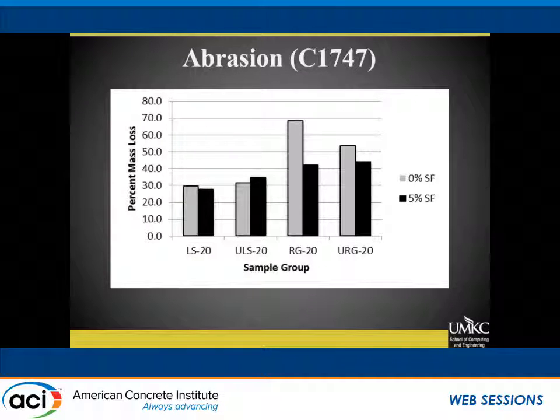Our limestone had, so there's our limestone. We didn't see any difference in 1747 abrasion with or without our silica fume. For our river gravel, though, we in fact did. So we had a substantial decrease in mass loss when we had our silica fume in there.